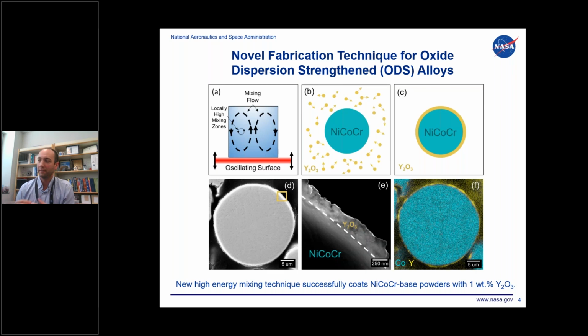The issue though is always how do you get your nanoscale oxides with your metallic powder into your 3D printer? What we came up with was using this new high energy mixing technique called resonant acoustic mixing. What we can do is take the metal powder, which in this case, starting our research, was nickel, cobalt, chrome, equal atomic. It's a very amenable alloy to 3D print and creates a really nice foundation of this ODS project moving forward.